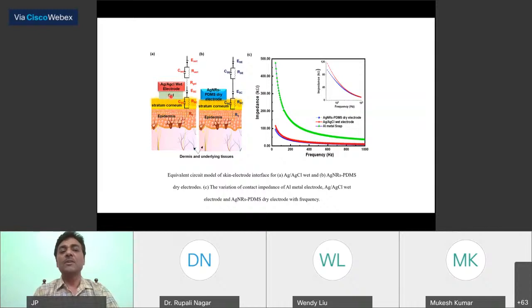That's why in industry they use conducting electrolyte gel here. In our case, we use silver nanorods. Another problem is that if the contact area moves a little bit, then you will have problems with electrical noise signals in the circuitry. In our case, because the nanowires are coming out, we can push fit them inside the skin, so they can peer a little bit inside the skin and move inside the skin. They get fixed there. Also, the large specific area reduces the electrode and skin impedance.